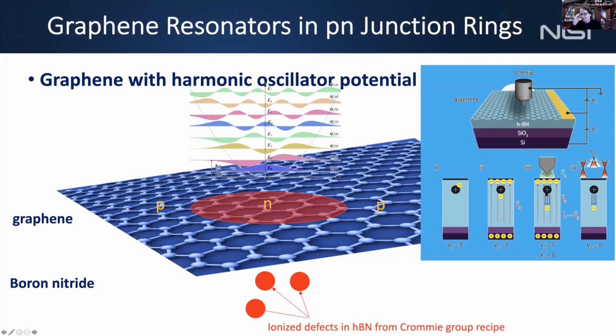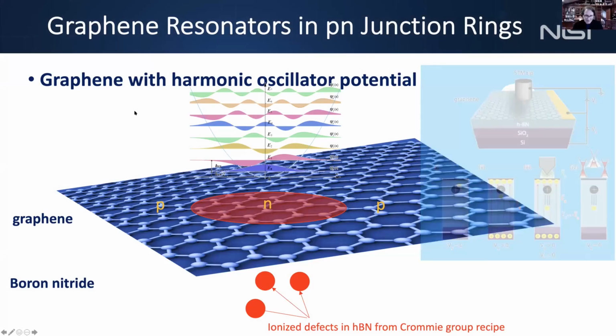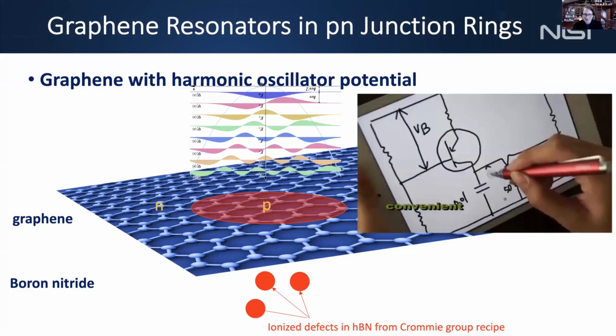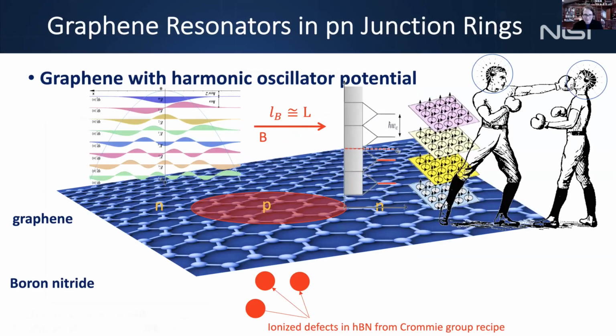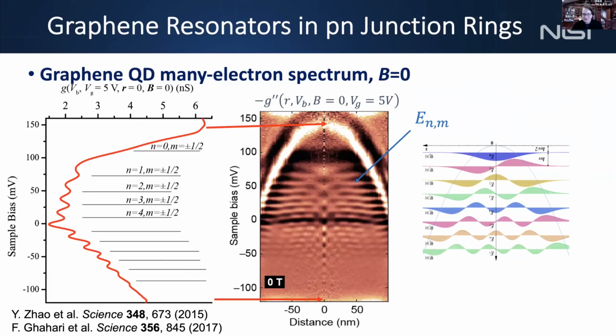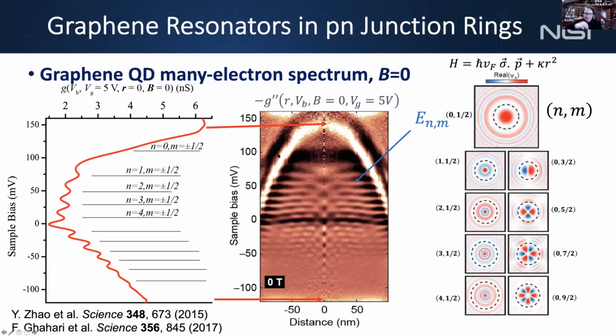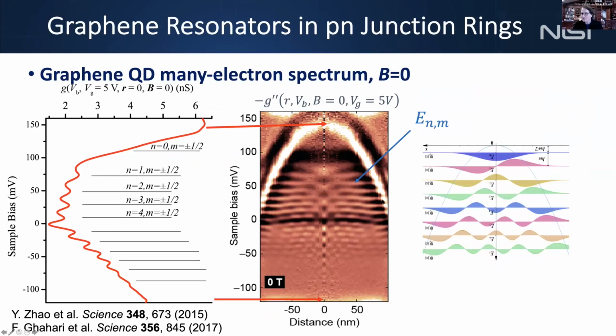So actually, you have to be careful now. If you have your probe at like 5 volts on graphene, you'd be writing patterns all over the place. But how circular does this get, and how sharp is the potential, the edge of your potential well? You can play with the size scale a little bit by the distance where you pulse it, but typically we find them on a length scale of about 100 nanometer radius.